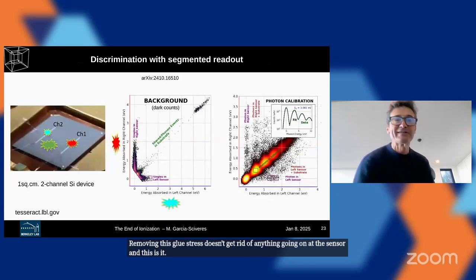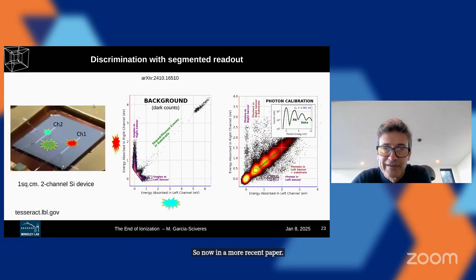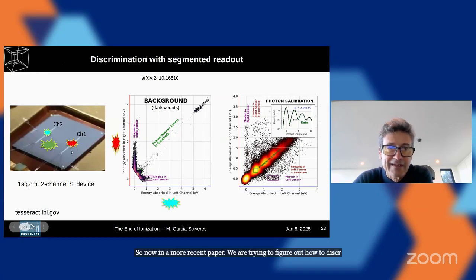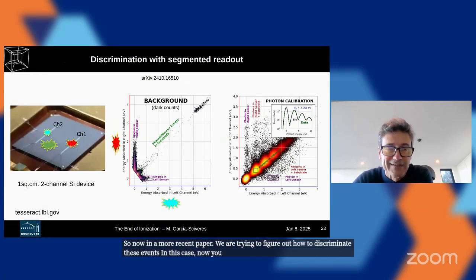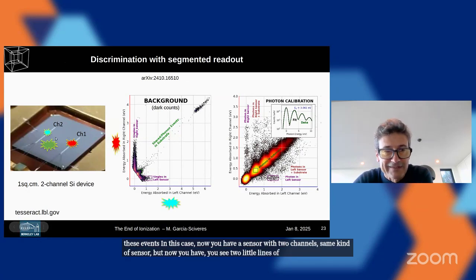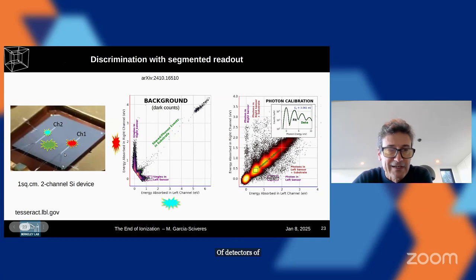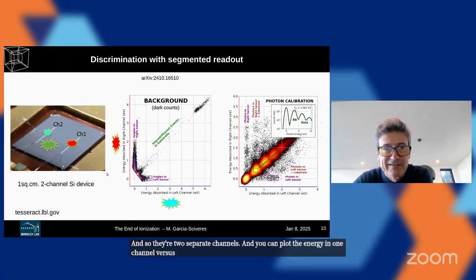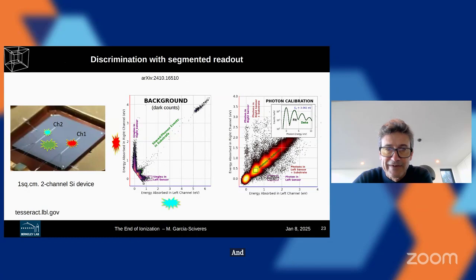So now, in a more recent paper, we are trying to figure out how to discriminate these events. In this case, you have a sensor with two channels, same kind of sensor, but now you see two little lines of aluminum detectors, quasi-particle assisted TESs. They're two separate channels, and you can plot the energy in one channel versus the energy in another channel, and you can see very clear backgrounds. These are dark counts, very clear dark count singles.